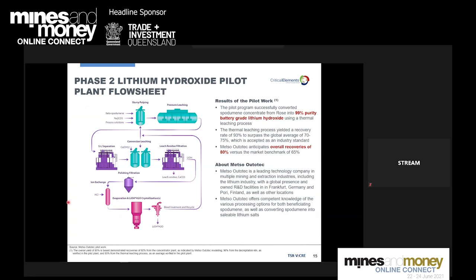Phase 2 is all about converting our spodumene concentrate into the highest quality lithium hydroxide monohydrate used in the manufacture of the cathodes for those high quality batteries. Pilot work on the Rose concentrate has already demonstrated a recovery rate of 93% in thermal leaching, which gives us an overall lithium recovery rate from ore to lithium hydroxide monohydrate of over 80% versus the industry benchmark of around 65%. New pilot work by Metso Outotec is about to begin and will focus on giving us new data points to reduce startup risk and aid in vendor selection.